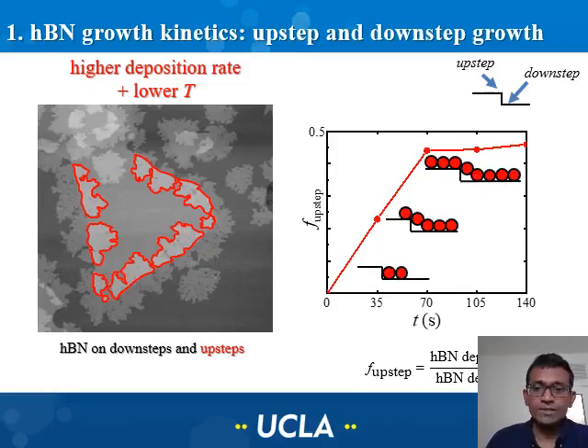And here on the plot, I hope you can see this. The fractional coverage along the up step is defined as the amount of hexagonal boron nitride that is deposited at the up steps divided by the total amount of hexagonal boron nitride deposited at all the step edges.